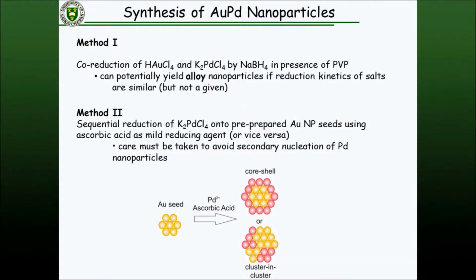The second method is to pre-synthesize gold particles and then do a secondary growth of a shell on those particles. That usually involves bringing in a weaker reducing agent such as ascorbic acid, and in controlled conditions we can get essentially the gold nanoparticle catalyzing the growth of the palladium onto its surface. You really want to avoid any possible secondary nucleation of pure palladium particles. That is, we want to grow from the gold. We don't want to form new particles of pure palladium. So we started with the co-reduction.